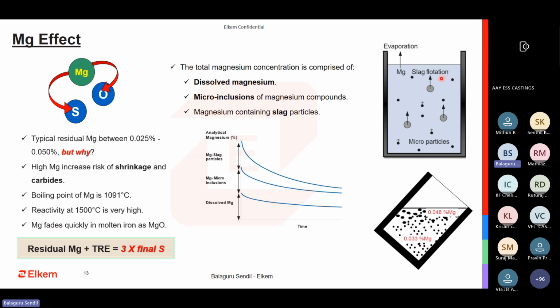So after ductile iron treatment, deslagging is very important. People tend not to do deslagging because the temperature drop is going to be there, but it is always advisable to do deslagging. An ideal foundry would keep the treatment ladle idle for 30-40 seconds after treatment and remove as much slag as possible before pouring. If you're going to have temperature loss, that's a different situation, and we need to find a way to isolate the temperature loss, which we will also talk about later.